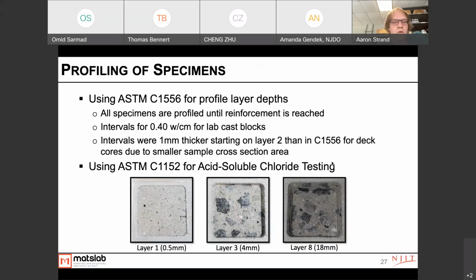The intervals were for a water cement ratio of 0.4, which is what these were cast at. And the intervals were 1 millimeter thicker for the cores that were extracted from the deck than what was specified. This was due to the smaller area of the cores, resulting in more powder needing to be collected in order to actually run the test. And we can see at the bottom what the layers look like as I ground down and extracted the powder from each layer.